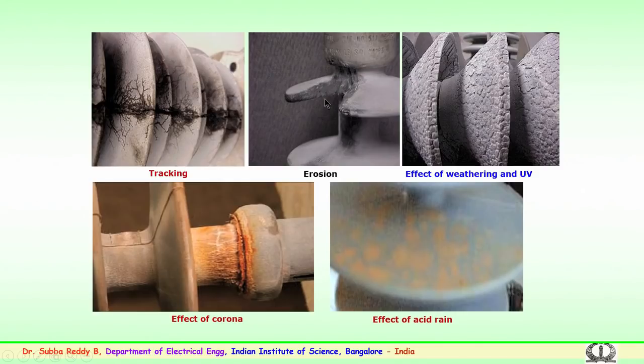The second is erosion. You can see the material peeling off over a period of time. This could happen because of several reasons: environmental issues, or continuous failures because of the material becoming harder and the entire material peeling. This surface erosion brings down the entire creepage distance and the flashover happens. Then there is the effect of weathering conditions, because of the sun, the ultraviolet radiation, or exposure to corona over a period of time. You can see the surface becoming stiff, becoming brittle, and the entire surface becoming hydrophilic, where it will be able to conduct and the failure happens.